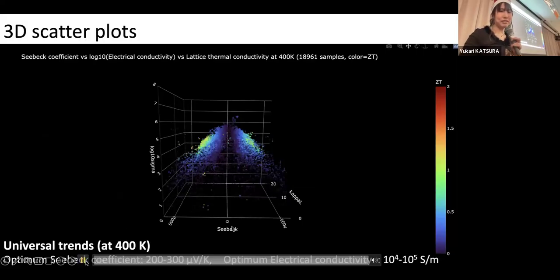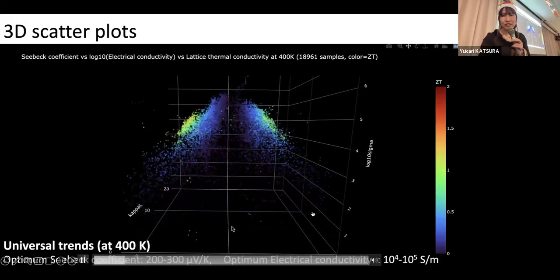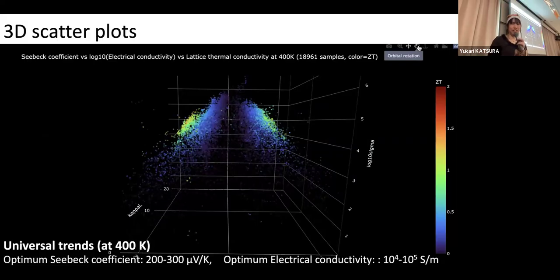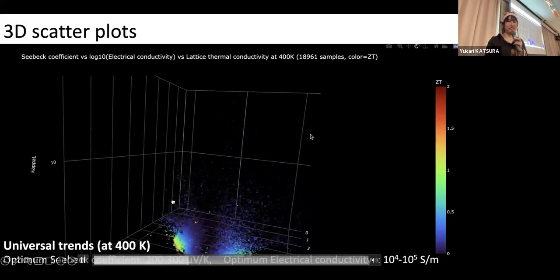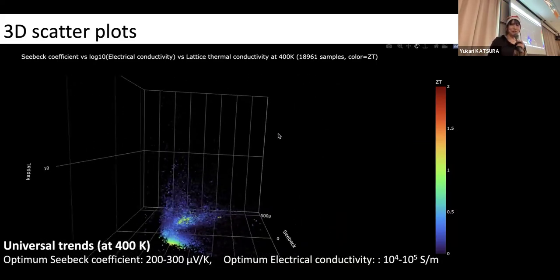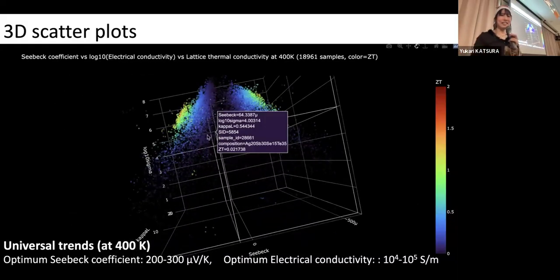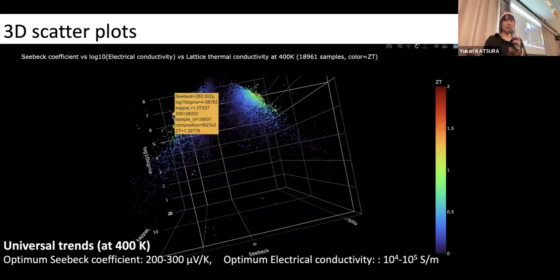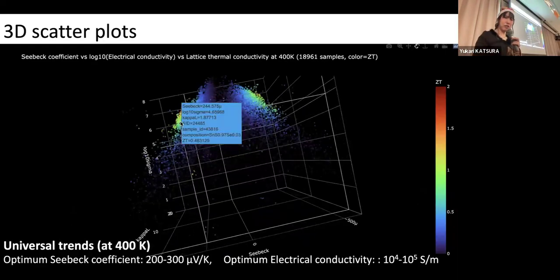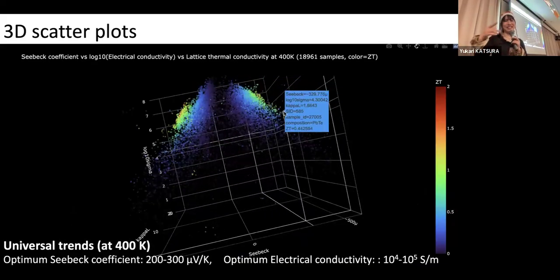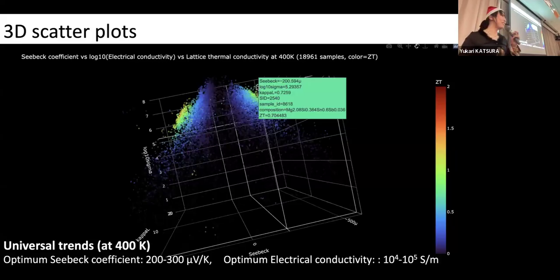Okay, so this is a scatter plot in 3D. The horizontal axis is Seebeck coefficient, and the vertical axis is the log of the electrical conductivity, and the depth is lattice thermal conductivity. And the color indicates ZT, and so regardless of the material family, we can see where the high ZT samples are located. So just by measuring one parameter, you can see if that can lie in the promising region or not. But there are also some outliers. So if you are more interested in outliers, you can explore those and think about why these are outliers and find new guiding principles. So I think overviewing the whole research field will be very interesting for materials researchers.